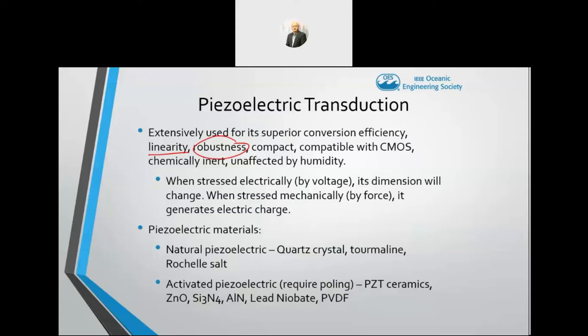However, even though piezoelectric transduction is quite robust, if we are using a ceramic-based piezoelectric material, it is not so robust, because we all know that ceramic is a quite brittle material. Once you drop your transducer, it will be gone. It is compatible with CMOS technology, of course. You can have built-in circuitry inside your sensors by using the piezoelectric mechanism. It is chemically inert and unaffected by humidity compared to other transduction mechanisms.